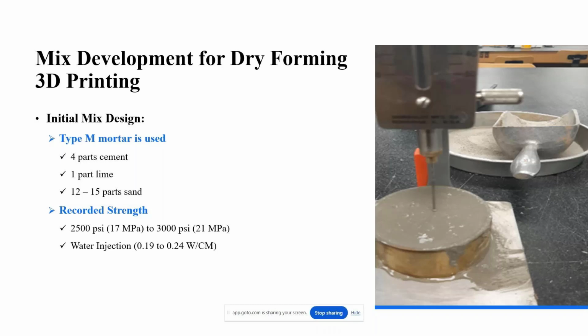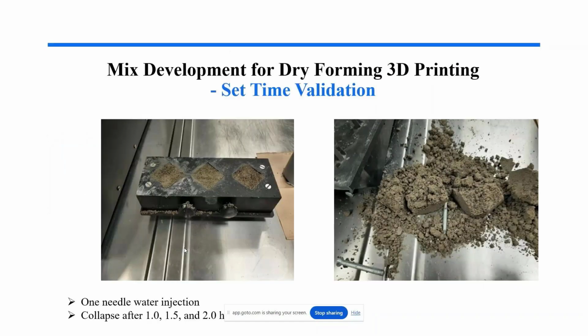So in order to fix this, we first thought about the mix design, and we tried our best so that we can arrive at a minimal compressive strength of 2,500 to 3,000 psi, and the water injection rate has to average anywhere between 0.19 or 0.2 to 0.24 water to cementitious material, and this is a ratio by weight. We formed smaller samples first. As you see, it's 2 inch by 2 inch cubes, and we used one needle for water injection. Because of the distance here, if you inject at the center, it will be 1 inch each way. And what we found is that up to 2 hours there has been a collapse.